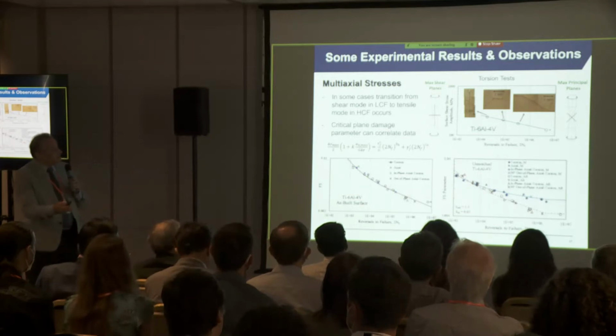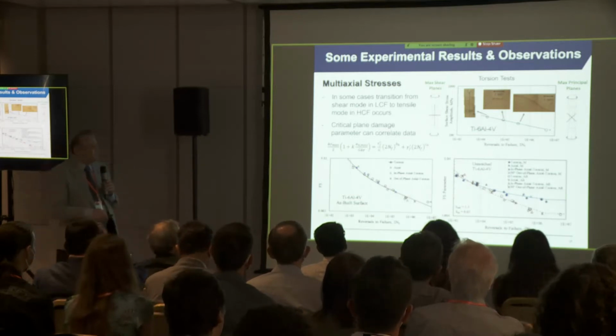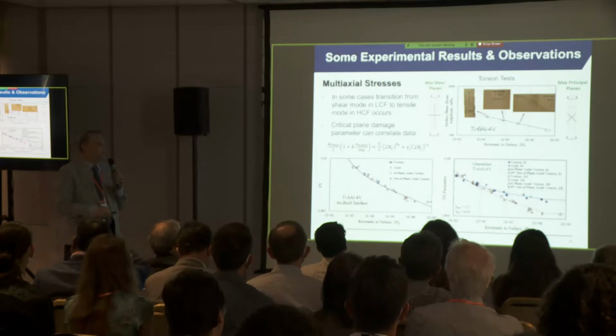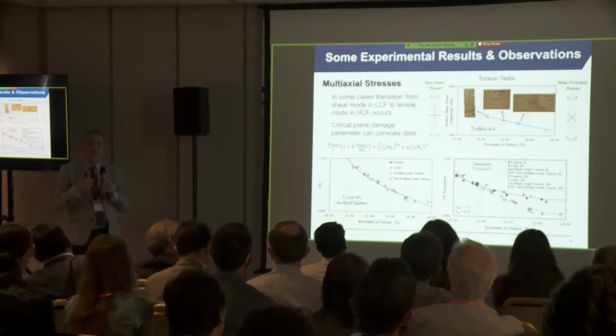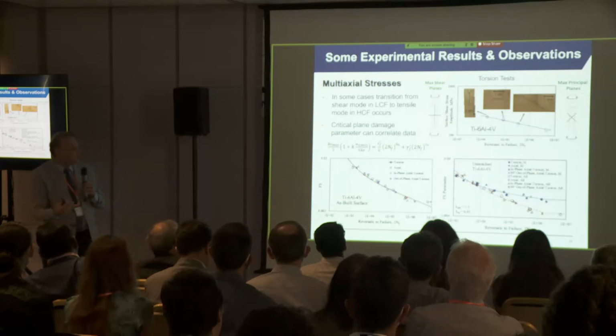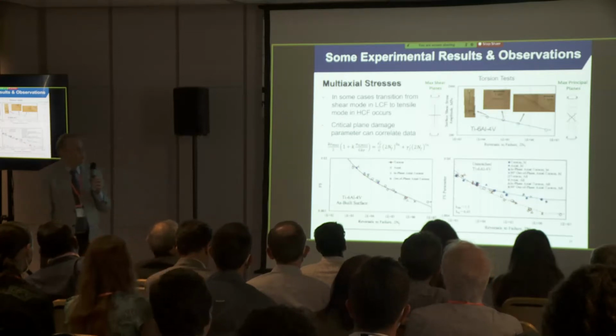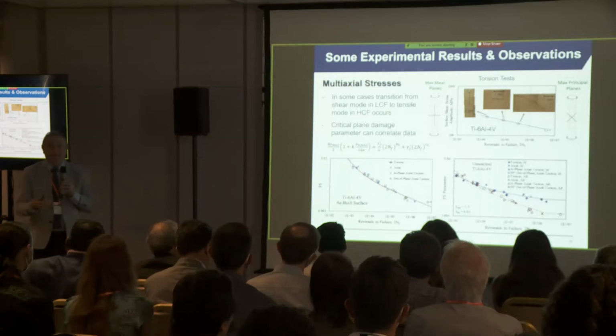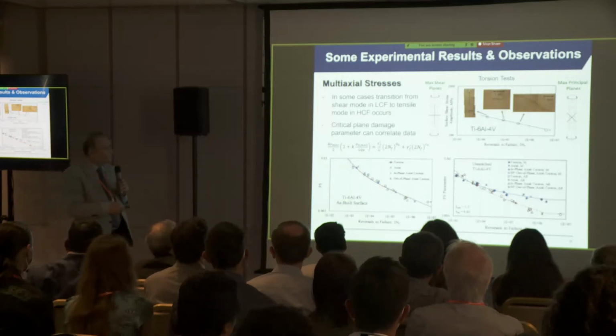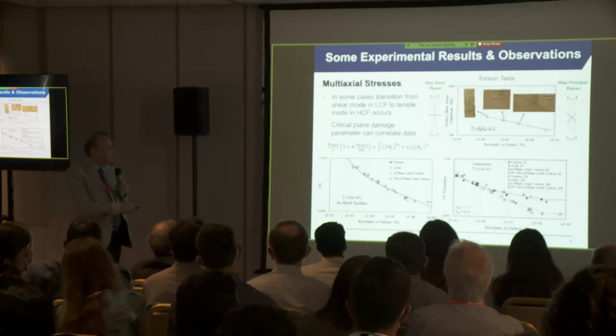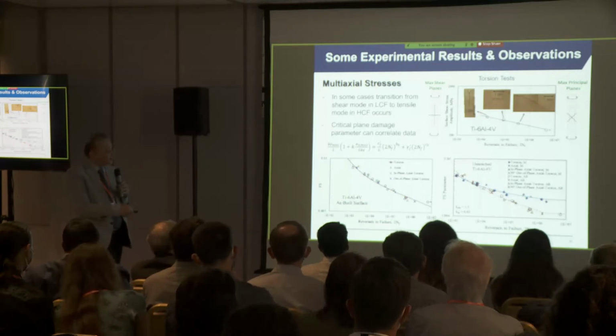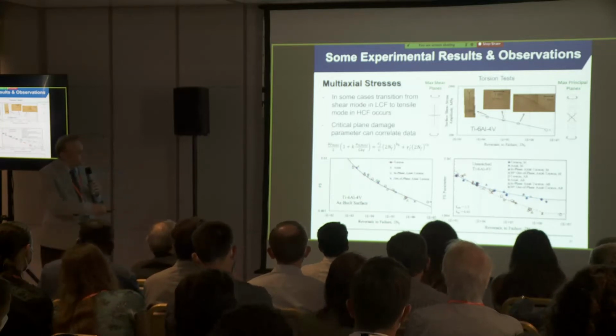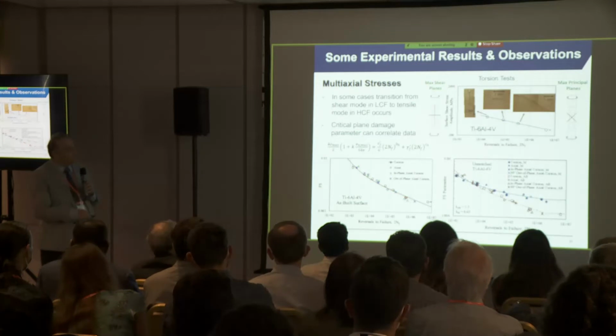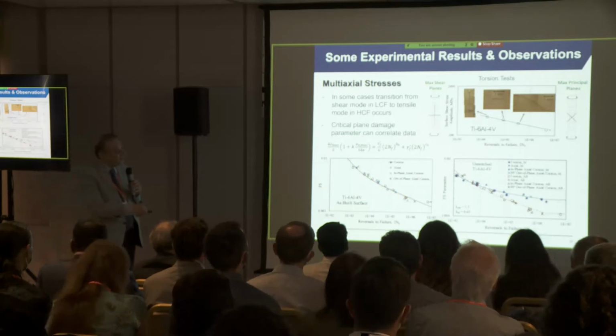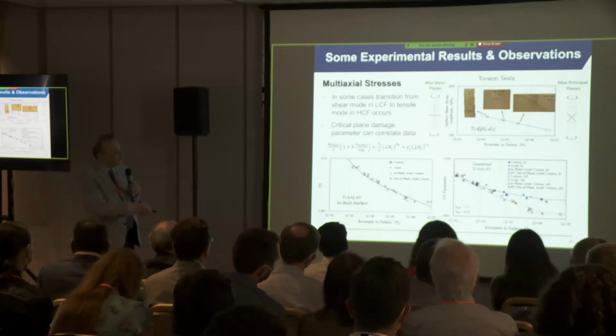Again, multi-axial stresses are very important when we are dealing with additive manufactured metals because a lot of the structures that we build with additive manufacturing are complex structures. That's one of the main benefits of additive manufacturing. But with complex structures come multi-axiality of stress. So again, using the right damage parameter is an important factor. So these are data from different stress states. They all come together using a critical plane approach. Similarly for as-built surface and for machined surface.